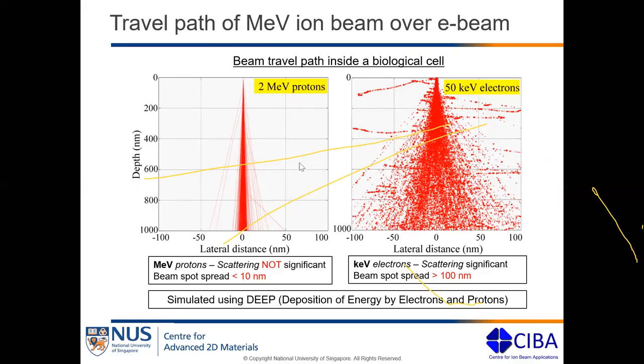So this is an example or the simulation of 2 MeV protons and 50 kilo electron volt electrons going through a biological cell. And you can see the 2 MeV protons go almost straight without much scattering. Whereas if you compare that with the electrons, you can see immediately that it scatters a lot, and the beam spot spreads over more than 100 nanometers. While if you look at the proton beam, you can see it is confined within 10 nanometers of beam spot.